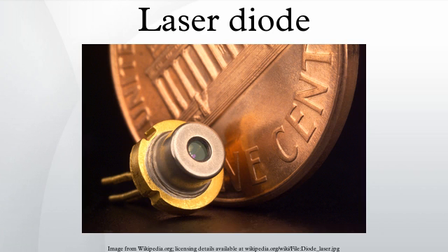Unlike a regular diode used in electronics, the goal for a laser diode is that all carriers recombine in the I region and produce light. Thus, laser diodes are fabricated using direct bandgap semiconductors. The laser diode epitaxial structure is grown using one of the crystal growth techniques, usually starting from an N-doped substrate, and growing the I-doped active layer, followed by the P-doped cladding and a contact layer. The active layer most often consists of quantum wells, which provide lower threshold current and higher efficiency.